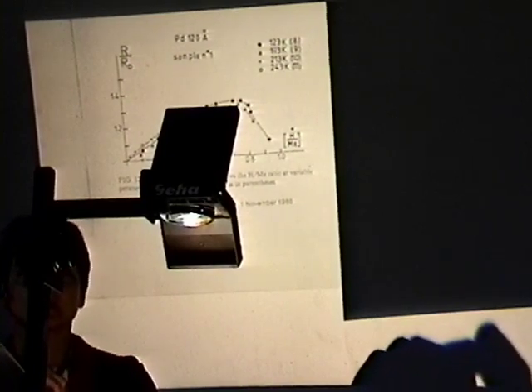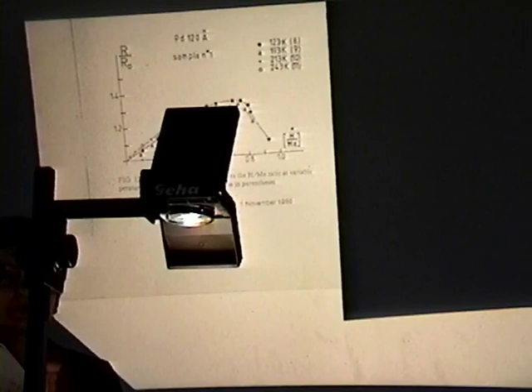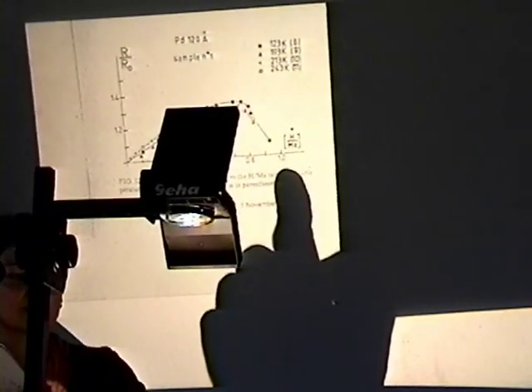This is very critical when working with this kind of film, because they tend to be stripped from the substrate during loading and deloading cycles. They are very delicate, not robust structures. So you can see, this is very similar to the sketch I showed you before on the Baranowski curves.